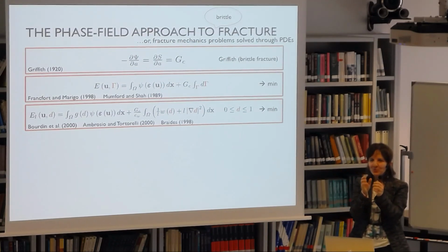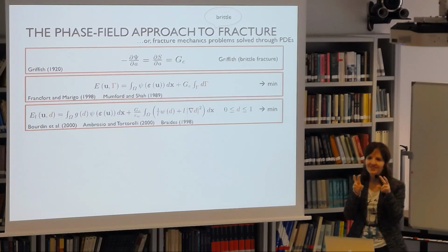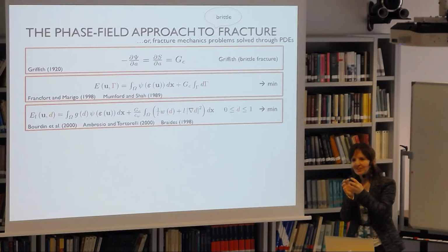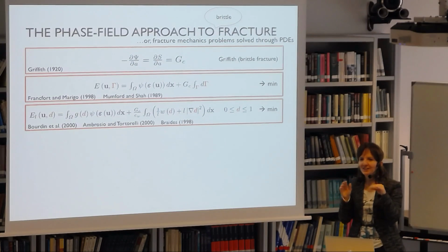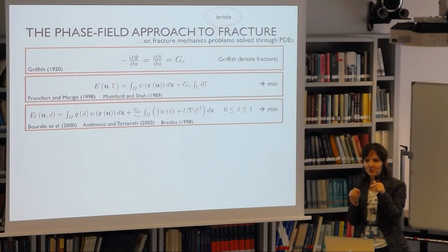If you have a pre-existing strong singularity, so if you have an initial crack, like in Griffith's setting, then you can show that the results are quite insensitive to L. In that case, you have a real convergence, in the sense that if L is small enough, results don't change with L anymore. But if you don't have a pre-existing singularity, then results are very sensitive to L.